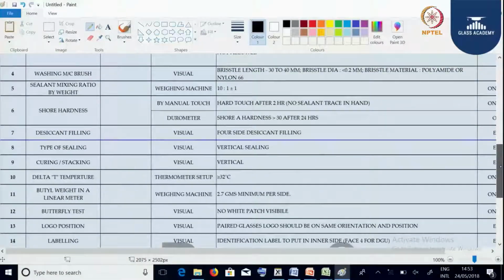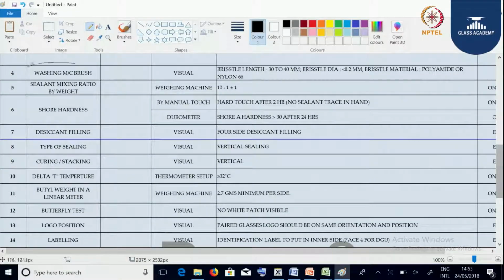Here we need to understand a few parameters, that is the washing machine brush quality. We need to check the sealant mixing ratio, measured with respect to volume and by weight, 10:1 plus or minus 1.